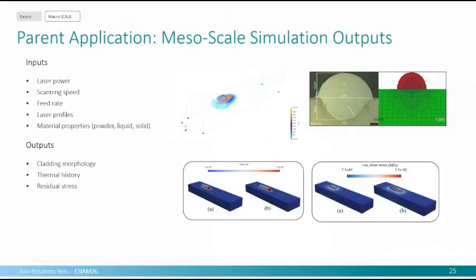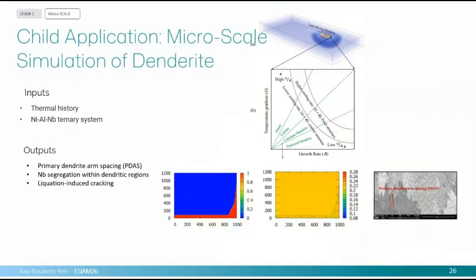So first step, with the experimental results that we had previously, we built this macro scale application where the inputs are the process parameters again, and the outputs are the cladding morphology, which was validated with previous results, the thermal history, and the residual stress. With this, the ambition gets bigger: if you have the thermal history, why not go to the microstructure and try to model the microstructure behavior? So we tried this, and we got some good results for the primary dendrite arm spacing.